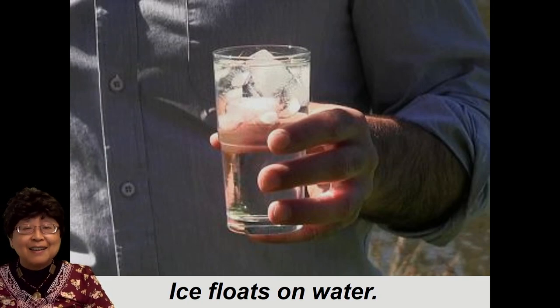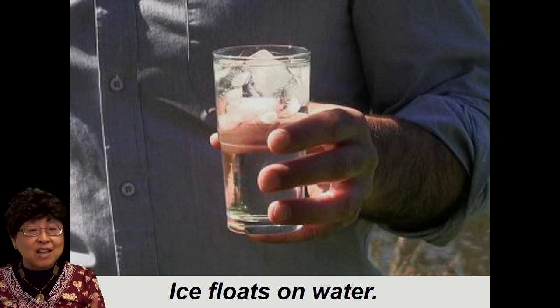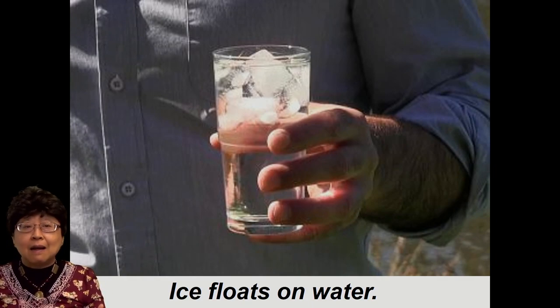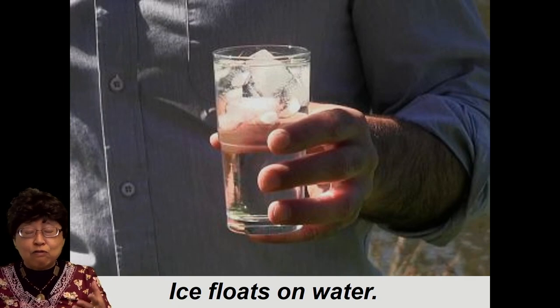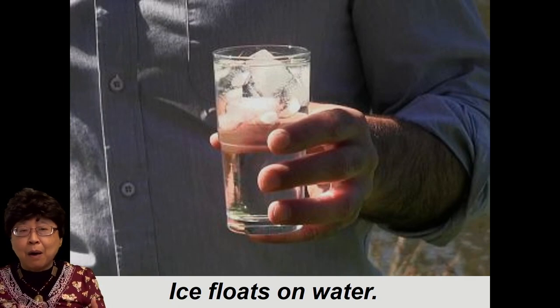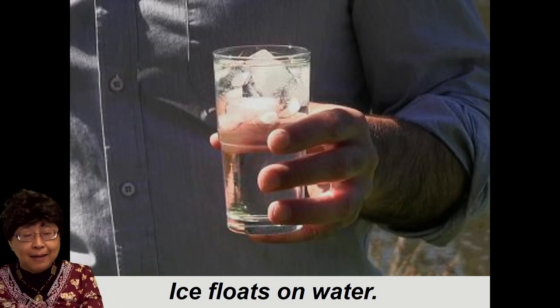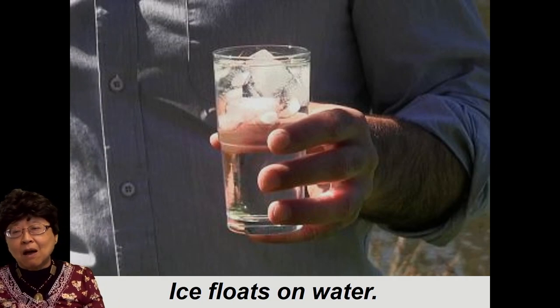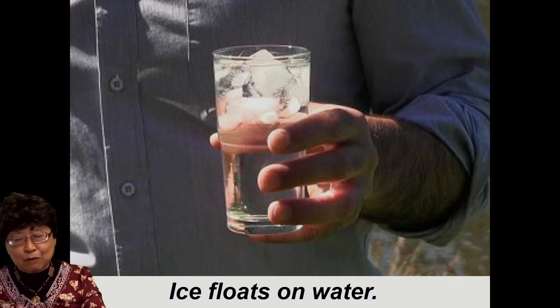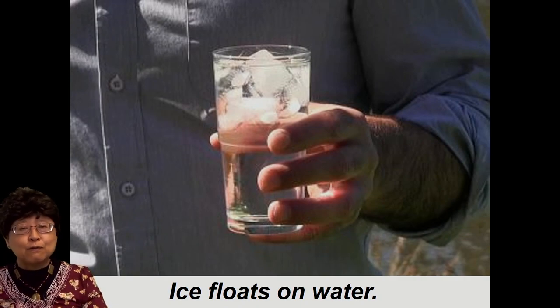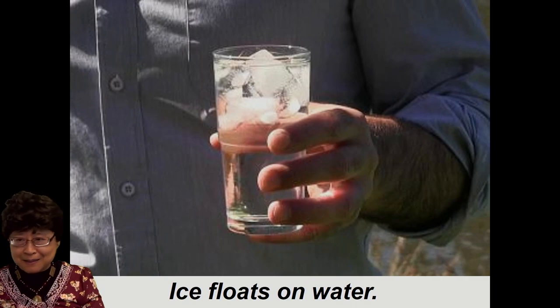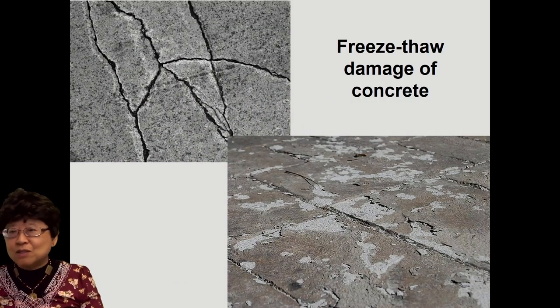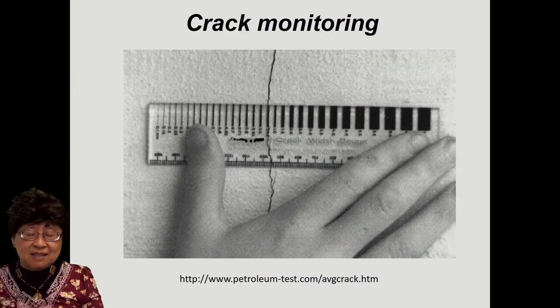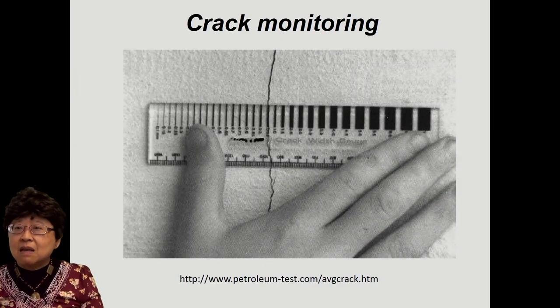For concrete, there's always some excess water in the concrete. And the concrete traps the water in there, and upon freezing, the water inside the concrete wants to expand a little bit. And so it causes cracking, particularly if you have multiple cycles of this freezing and thawing. It's like fatiguing. And so you get these cracks. In wintry places, this is very, very common.